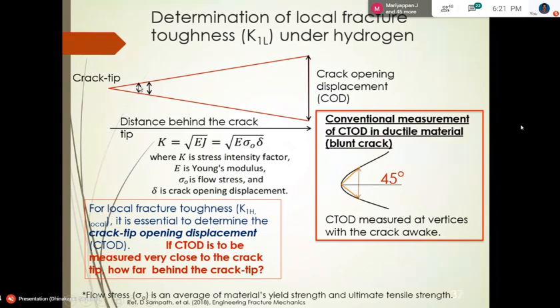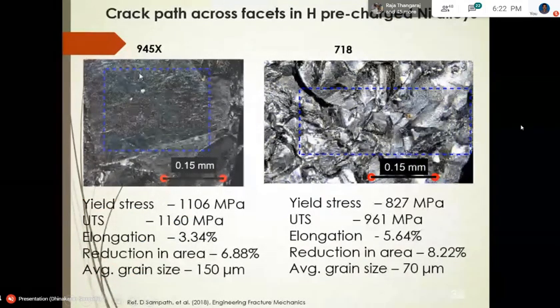So we used the crack tip opening, but from some distance behind the crack tip. In one case, 0.05 and 0.1 millimeters. Some more research is required to find out at how much distance we need to measure. But mostly it is to have this 45-degree angle to meet this criteria. So this is the formula: K is the square root of Young's modulus times flow stress times tip opening. We did that for 945X and 718. So these are some details.